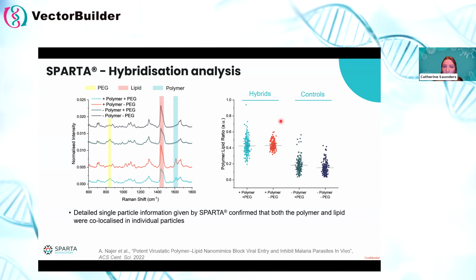What you can see here on the right-hand side are the controls, with no polymer. And on the left-hand side are the two hybrid, or hopefully hybrid, particles. Again, there's this average line, which is what you'd get from the bulk methods, and then each of these dots is an individual particle. What's very clear from this analysis is that both of these hybrid formulations were showing clear polymer signal across all of these particles. So from this quite simple analysis, we could confirm that hybridization was occurring and these particles were made of both lipid and polymer components.